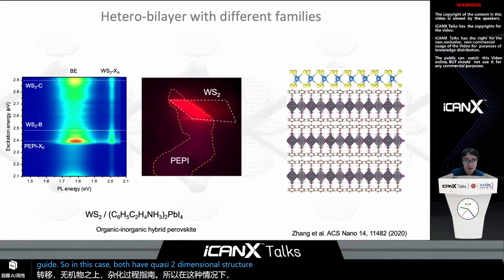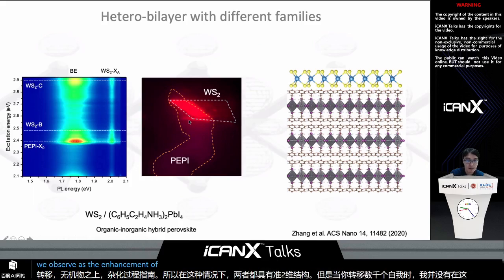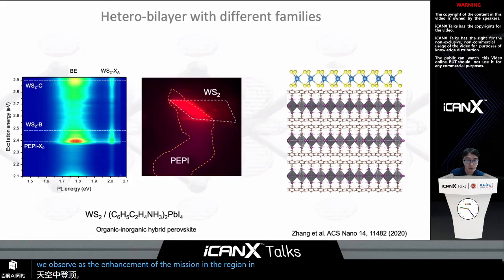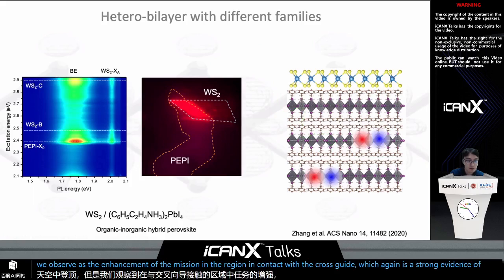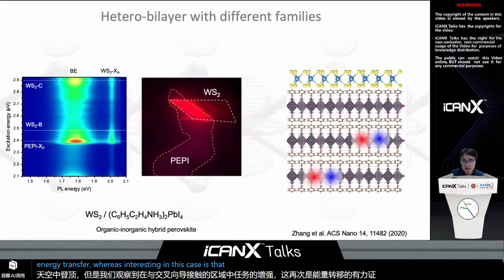But when you transfer tungsten sulfide on top of this perovskite, what we observe is the enhancement of emission in the region in contact with the perovskite, which again is strong evidence of energy transfer. What is interesting in this case is that the enhancement factor is more than what we had initially expected,